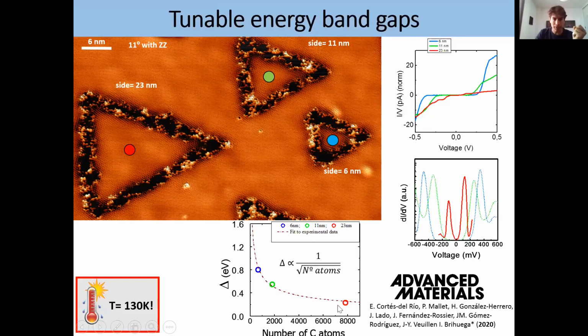So if we analyze the dependence as a function of the square root of the number of atoms, that's what we expect for massless Dirac fermions. This is what we get, and we can also do tight-binding calculations, and we get this very nice dispersion here, exactly the same as we have from our experiments. So it is really possible to open band gaps, but there are also many other things. In principle, you could think of coupling the different graphene dots or doing many other different things.